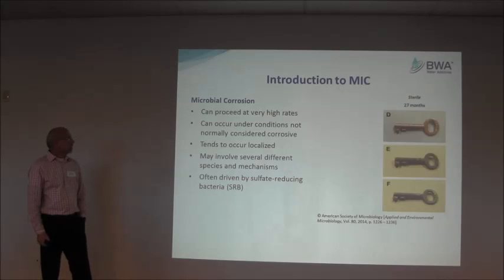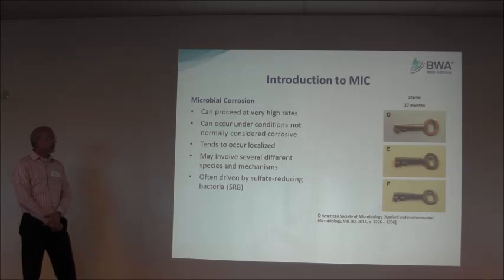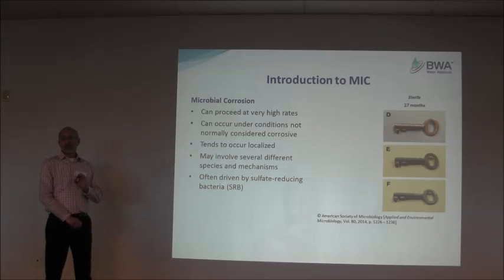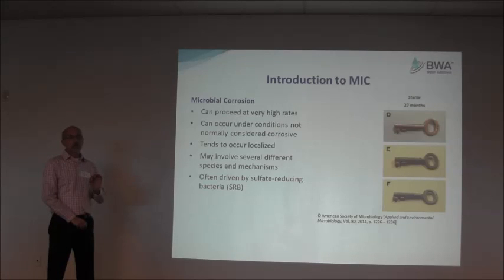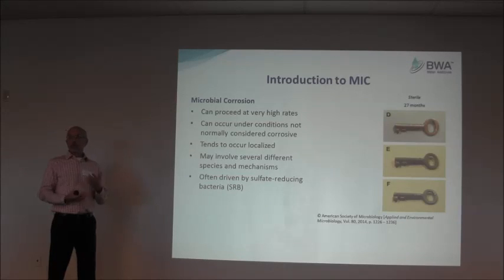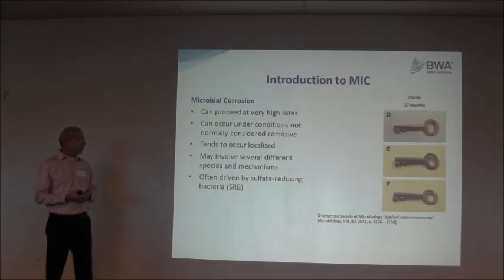So, introduction to MIC. MIC can proceed at a very high rate, especially in waters that don't appear very corrosive. It tends to occur in a localized manner, so you get pitting corrosion with MIC — one of the worst types of corrosion because you can get through-wall perforation very quickly. It involves many different organisms and usually a consortium of organisms, but there's one type that's very correlated with MIC: the sulfate-reducing bacteria.